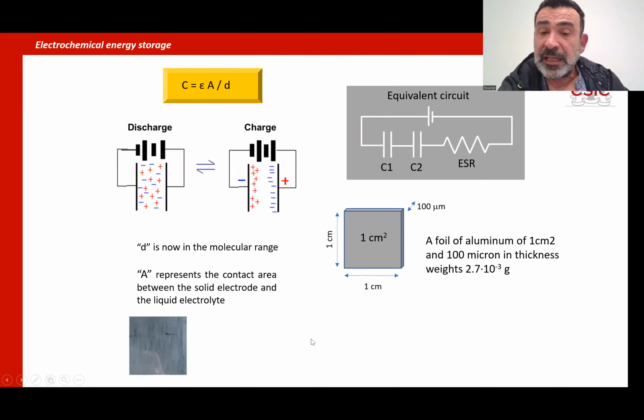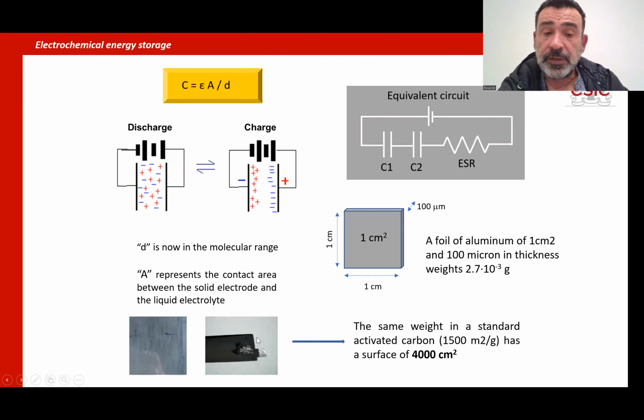But what happens if you put a little amount of activated carbon on top of the aluminum? If you put, for example, just 2 or 3 milligrams of standard activated carbon, the surface area is now 4,000 square centimeters. If the electrolyte goes into the porosity of the carbon, you have increased A, the surface area, by 3 orders of magnitude.